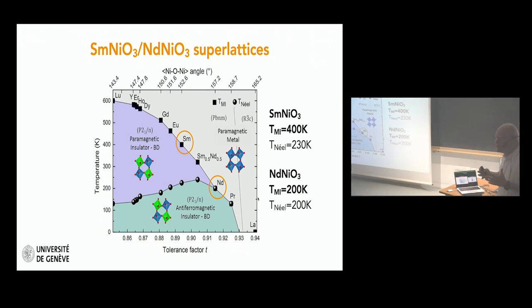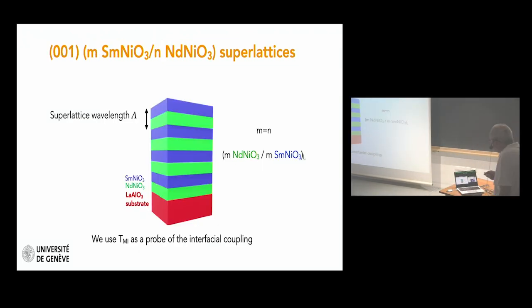And when we started this project, we saw that by making these superlattices, at each interface these distortions have to adapt. And we were wondering what will happen. So what we did, we realized superlattices of these materials. The materials are grown on lanthanum aluminate, and you make different layers. Each layer has the same thickness: M unit cells of neodymium nickelate, M unit cells of samarium nickelate, and what you're changing is the wavelength of the system, or the thickness of each layer.